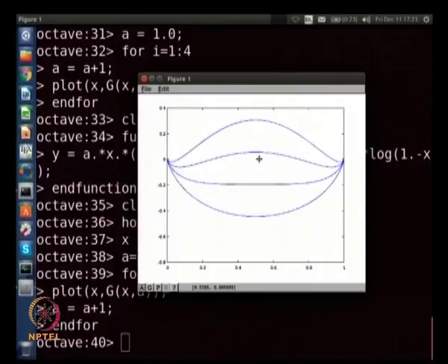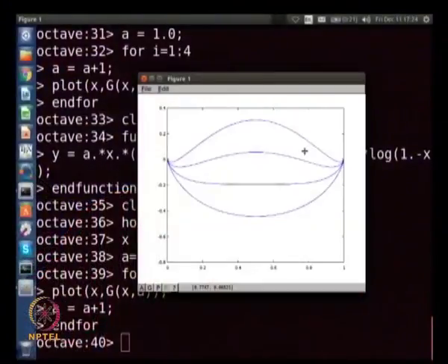So, this is the kind of curve that you would have seen in materials thermodynamics courses. For example, you can go and take a look at Gaskell's textbook, the regular solution chapter, in which you will see something like this, and they will show you that there is this critical point about 2 for omega by RT value, and below that you will have this two phase region, above that you will have a single phase region. So, that is basically the same information that we are showing, but here we are showing it in terms of the normalized free energy versus composition.